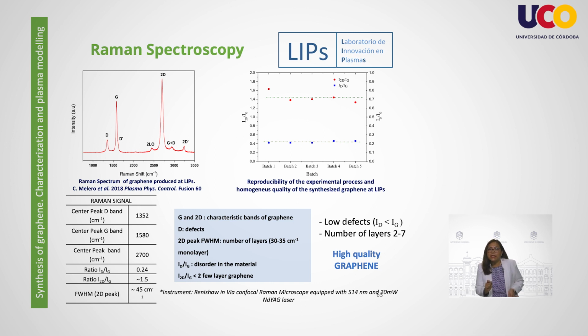Now, the D peak at 1352 can be related to defects, which refers to the presence of sp3 carbons in the basal carbon plane, such as in disordered graphene and graphene oxide. And finally, the width and the height of the 2D peak can relate to the number of layers. This Raman technique is widely used in industry and laboratory to identify the graphene characteristics through the Raman ratios D over G and 2D over G.